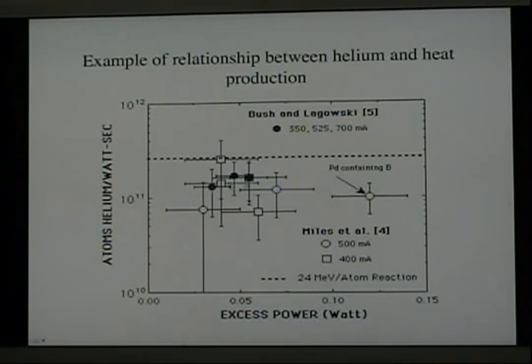Well, notice that the data fall in a region about 50% below this. In other words, half the energy is missing. This occurs because the helium was measured only in the gas. Any helium that remained within the palladium would not be measured. So this is exactly what you'd expect if a nuclear reaction took place on the surface of the palladium. Half of the energetic helium would go into the liquid and then into the gas where it would be collected, and the other half would go the opposite direction into the palladium where it would be captured and not measured.